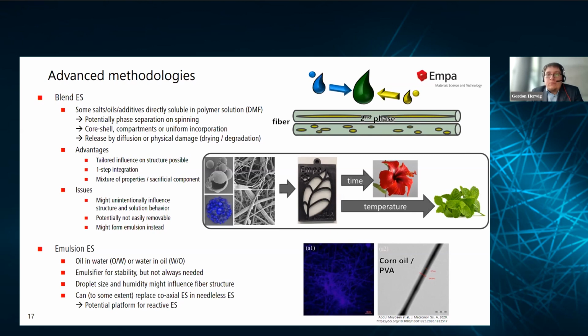With electrospun membranes, you don't need to worry about it too much because simply there's not enough material. It degrades so quickly and the body gets rid of it relatively quickly that it shouldn't be a problem. You can theoretically also, if you use a patch, for example, external, use something that's way more stable, for example PVDF-HFP or something like this, as a matrix, and then you mix another polymer inside. Problem is with this, let's say PVDF-HFP would certainly repel the drug, and then you have another polymer in there that can absorb the drug or maybe encapsulate it better. The problem with that, you don't know what's going to happen until you actually try it.